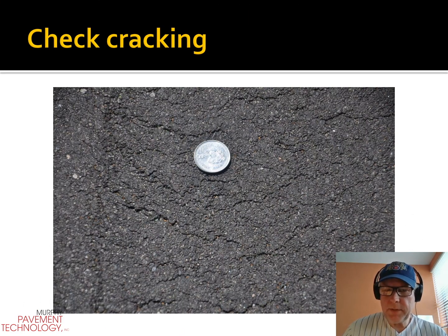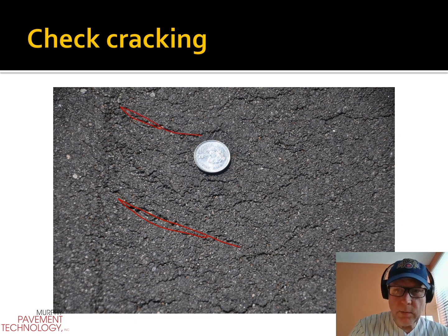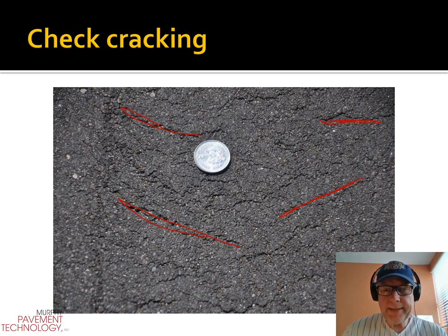I told you I would be talking to you and showing you some photos of check cracking, and you can see all those tiny cracks going across the asphalt. So now there's tens of thousands of little areas where moisture can get into the asphalt and get trapped. Check cracking cannot be amended. Check cracking will almost always guarantee you a failure, whether it's on a roadway, a runway, commercial industrial parking lot, and certainly athletic asphalt as well.